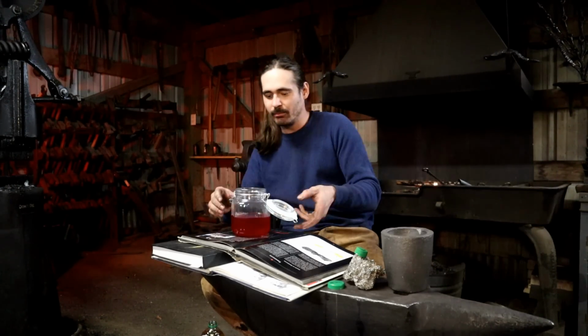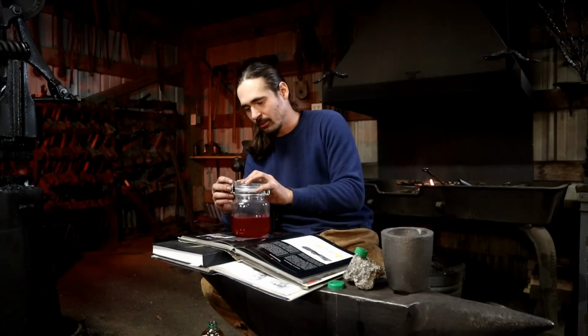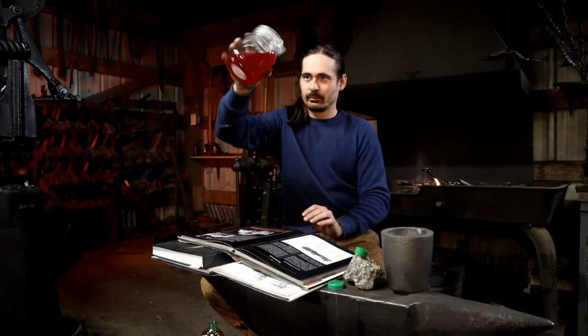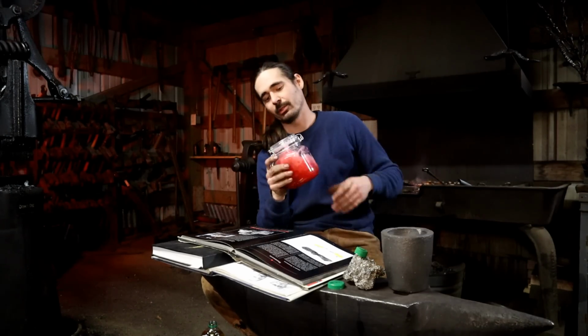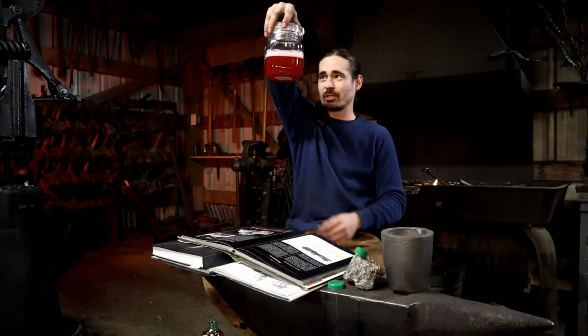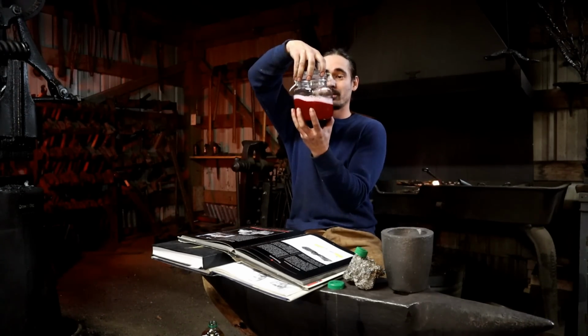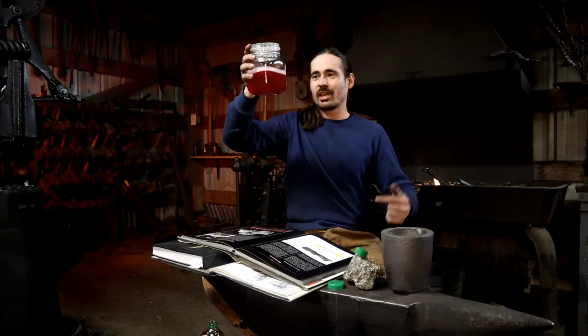And immediately, our crucible starts melting. It's melting. I'm making my crucible steel. Now, all my sulfur and phosphorus did not get to leave. In fact, since a crucible steel making process is essentially a high temperature pressure cooker, all my gases have penetrated even further and evenly distributed themselves into my material.